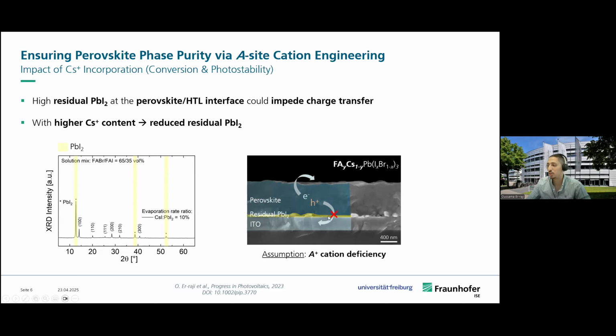And to test whether this is true, we then tried to increase the amount of cesium in our perovskite, and this we can do just by increasing the amount or the rate of cesium iodide that we evaporate in the first step. So what happened when we tried this, as you can see, going from 10%, so cesium iodide here is 0.1 angstrom per second, here we go to 0.12, and here 0.15 angstrom per second, you can see that we can gradually, slowly but surely, reduce the amount of lead iodide in our film.